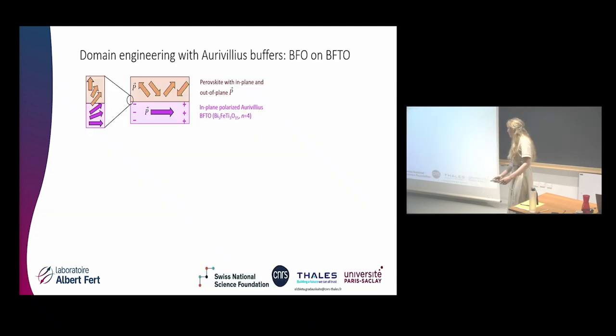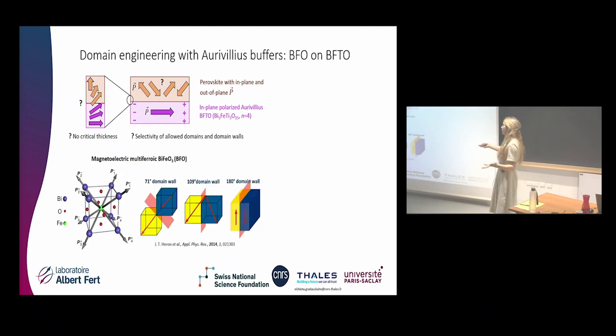Then we went one next step. Okay, we had BTO. This is nicely out-of-plane polarized. Now can we go one step further and take a multiferroic that has many domain variants? And that is BFO. First of all, we want to see if we still have no critical thickness, and then can we have some selectivity of which domains and domain walls are allowed, because of course here we have the uniaxial in-plane polarization along one axis, and can we have any selectivity? And BFO, as you might know, if we consider a pseudo-cubic unit cell, it has 8 polarization directions along the diagonals and different domain walls.